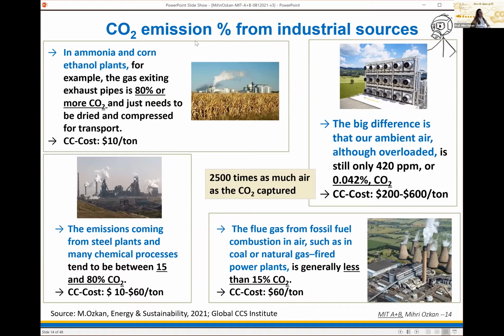Let's look at these industrial emission sources. One of them is the ammonia and corn ethanol plants. If you look at the gas coming from their exhaust pipe, 80% of that is carbon dioxide. If we were to capture this at the source, the cost to us is around $10 per ton. And if we have a steel plant, in this case the concentration is between 15 to 80%, and the capture cost is anywhere between $10 to $60 per ton. In the case of flue gas, from coal or natural gas fired power plants, the contribution is around 15% carbon dioxide, and the cost of capture is around $60 per ton.